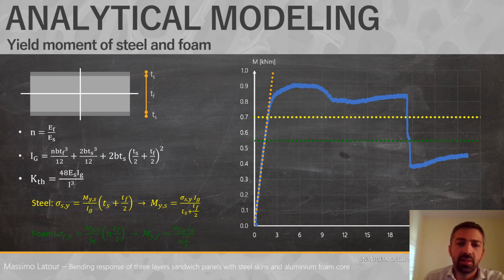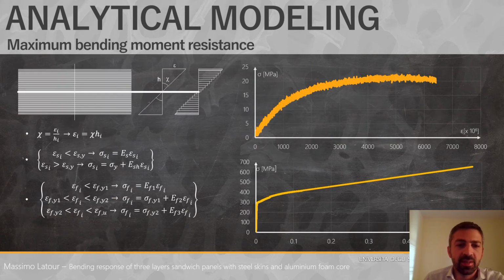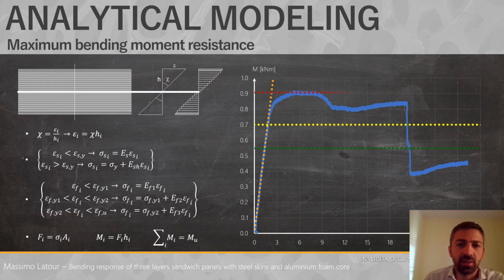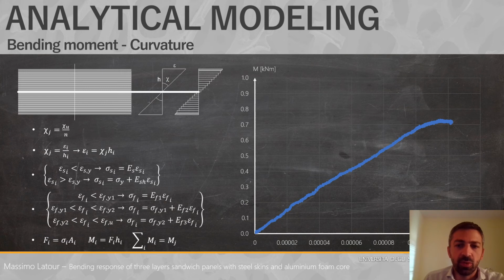For what regards the ultimate resistance, a step-by-step full integration procedure was carried out, integrating the stress and strains along the cross-section, setting a procedure based on the construction of a moment curvature curve. This moment curvature curve was developed, predicting also the ultimate resistance of the panel. Also, this ultimate resistance showed to provide a very accurate prediction. In addition, we were able to compare the moment curvature measured during the test with the moment curvature predicted by the analytical modeling. The matching was really accurate also in this case.